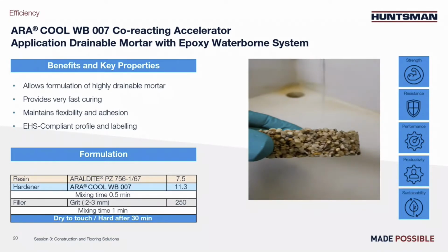So here we have an example of how to use this new Aracool waterborne 007 as a drainable mortar. So we did a simple formulation presented here. Basically the standard waterborne resin Araldite PZ 756-1/67, the pure Aracool waterborne 007, and some grits. The mix was done quickly, and after 30 minutes, the product was hard, with still a good level of flexibility, helping the adhesion between the small stones. Due to large porosity, water is going through, as I'm trying to show you now.